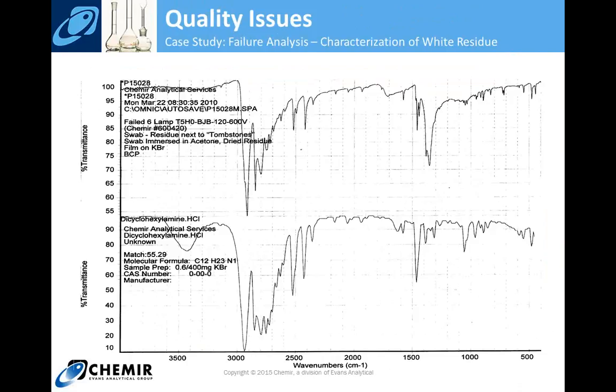Now, doing a more focused analysis and looking under optical microscopy, we saw some small amounts of white residues present in the cracked regions of these failed tombstones. We isolated a very small amount of this material, did another chemical fingerprint with IR, and had a very good match, at least a partial match, for a specific chemical, dicyclohexylamine. So the IR showed some chemical change of the polymer, and a small amount of foreign residue that we saw under microscopy showed a specific chemical that shouldn't be part of a polycarbonate. Dicyclohexylamine is not an additive or stabilizer or process aid. It's definitely a foreign chemical. And here's the structure for DCH.